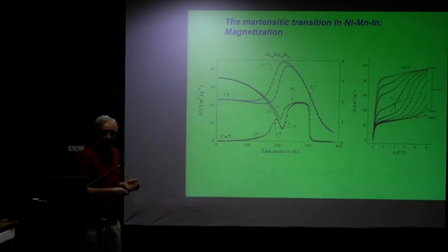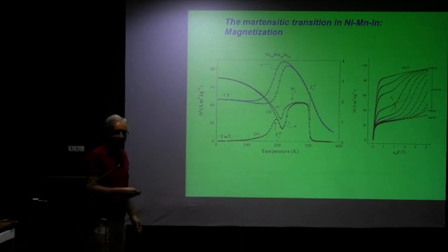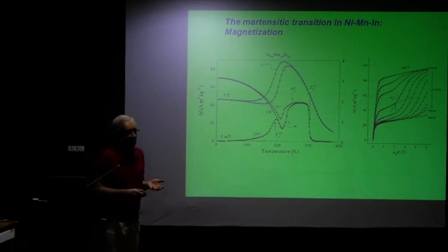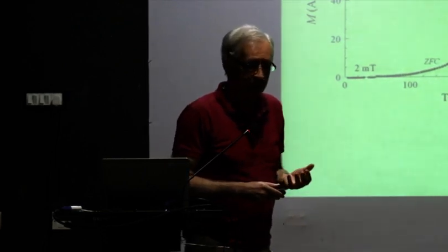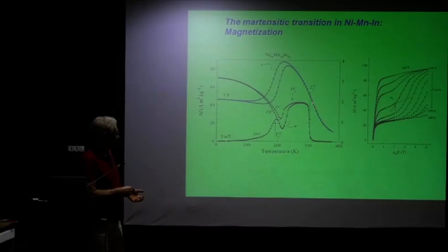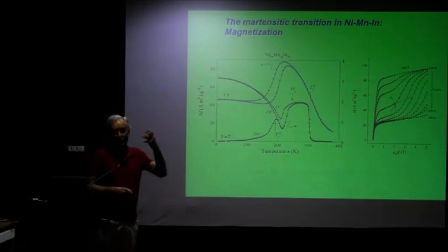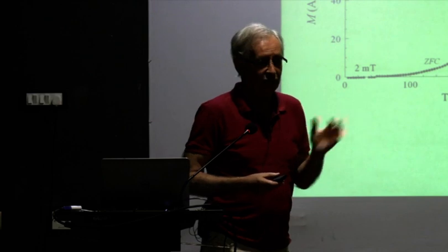There has been some controversy in the literature, where people have called this state a paramagnetic state based on Mössbauer experiments. Indeed, it is a disordered state, but thermodynamically it would not be possible to go from a ferromagnetic state to what we know as a paramagnetic state, because a paramagnetic state is where all the spins fluctuate.